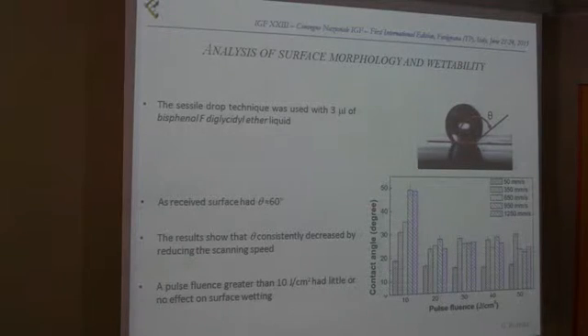And because the final application is the adhesive bonding technology, of course, we need to verify if we could modify, let's say, the chemistry of the surface and make it more hydrophilic, because that's what we want. So if the adhesive can, of course, penetrate better of the surface, so have a deep molecular interaction with the surface, we can have a higher quality joint, so a more resistant one. And the contact angle, as you can see from the figure, is going to decrease, so the surface is going to become more hydrophilic if we decrease the scanning speed. As for the pulse fluence, we cannot see really a huge difference starting from 20 to 50. So from just these results, we can tell that once again, the speed has a higher influence on the changes than the pulse fluence.